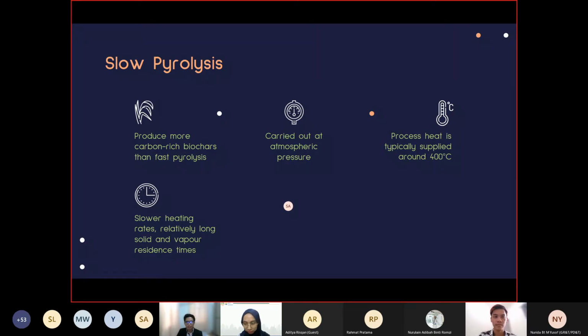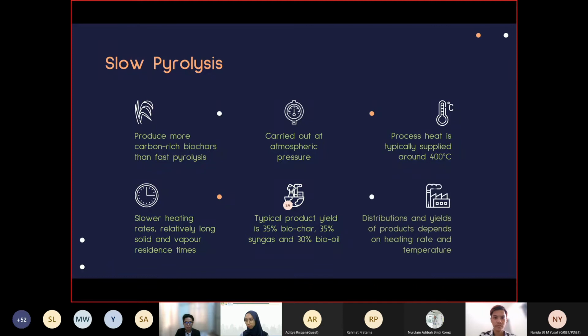During the pyrolysis process, the natural polymeric constituents such as lignin, cellulose, fats, and starch are thermally broken down into three different fractions: 35% biochar, 35% syngas, and 30% bio-oil. Depending on the heating rate and temperature, different distributions and yields of the aforementioned fractions can be obtained.